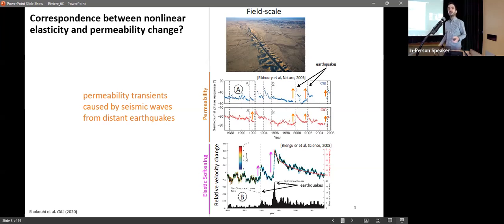And then at the same time, if we monitor the wave speed of the subsurface, we see a change in the wave speed whenever there is an earthquake. When it goes up here, the axis is inverted, so the velocity drops. So whenever there is an earthquake, the medium becomes a little bit softer, and then it recovers back to the initial value, or not if there is permanent damage. If the system was linear elastic, you would get a constant elastic modulus, and therefore you should expect a constant elastic wave speed, right? So the wave speed shouldn't change over time if the system was linear elastic. All these changes in wave speed are related one way or another to the nonlinear elastic properties of materials.